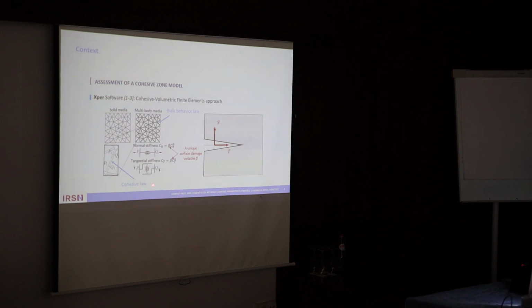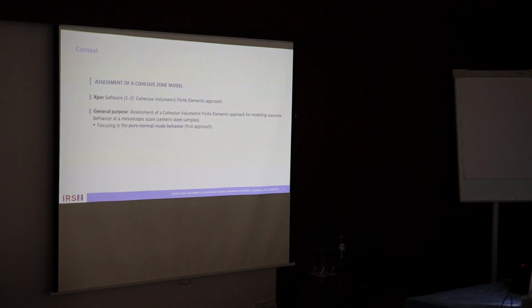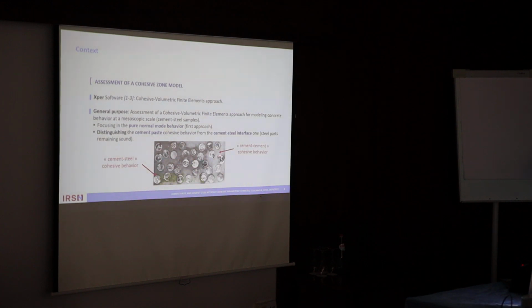In addition to the cohesive law in this particular approach, we use the bulk behavior law in the finite element for modeling volumetric strength. So the general purpose of this study was to assess the cohesive volumetric finite element approach for modeling concrete behavior at a mesoscopic scale, and in particular the concrete made of cement-based matrix and containing steel inclusions. In this presentation I will focus on the pure normal mode behavior, and I will distinguish the cohesive behavior inside the cement paste from the cohesive behavior at the interface between cement and steel inclusions.